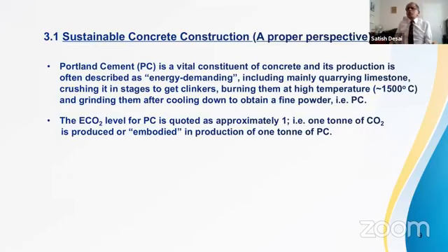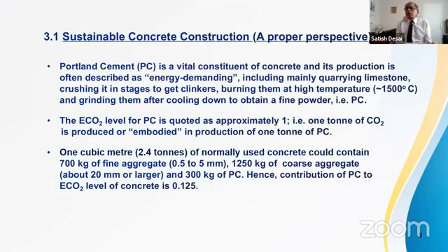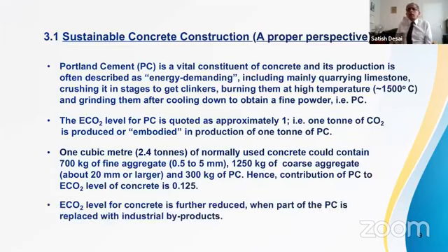The ECO2 level of PC is quoted as approximately 1. That is 1 ton of carbon dioxide is produced or embodied in production of 1 ton of PC. In ECO2, E means embodiment of carbon dioxide. 1 cubic meter, that is 2.4 tons of concrete, can contain 700 kilogram of fine aggregate, that is 0.5 to 5 millimeter, 1250 kilogram of coarse aggregate, 20 millimeter or larger, and 300 kilogram of PC. That means contribution of PC to ECO2 level of concrete is 0.125. This level can be further reduced when part of the PC is replaced by industrial byproducts. We'll see that in a few minutes.